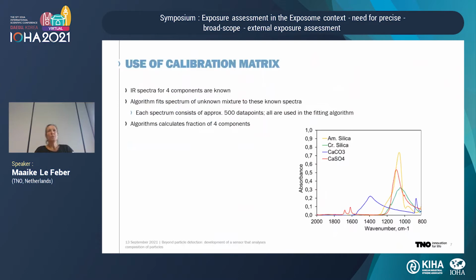So we developed a calibration matrix. So in fact, what we did is develop an algorithm that fits the spectrum of an unknown mixture to the known spectra. And by that, it can calculate the fraction of each of the 4 components.